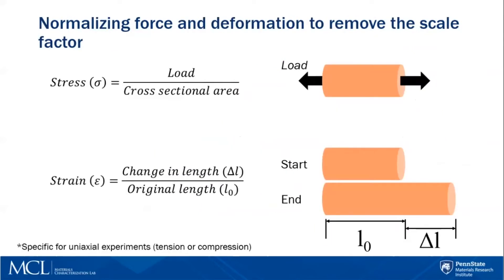With mechanical characterization, you do not talk about the load or force or deformation that is applied to your material, because these parameters are dependent on the size of your sample. You need to normalize to remove any sort of scale factor. So for stress, which is your load divided by your cross-sectional area, and strain, which is your change in length over your original length, these parameters are commonly discussed rather than load or deformation. So you actually measure the load and deformation, but you report your values in terms of stress and strain to remove that scale factor.